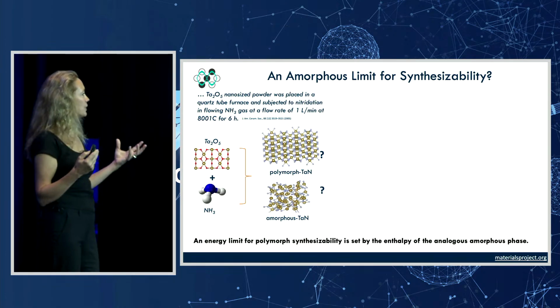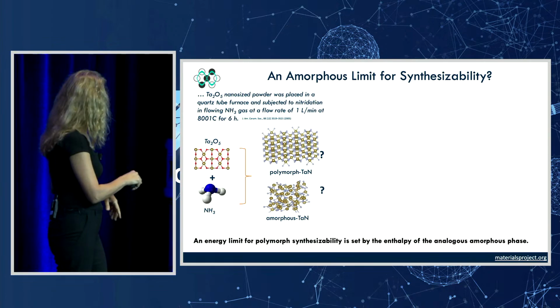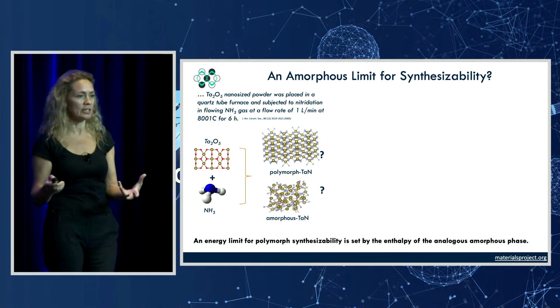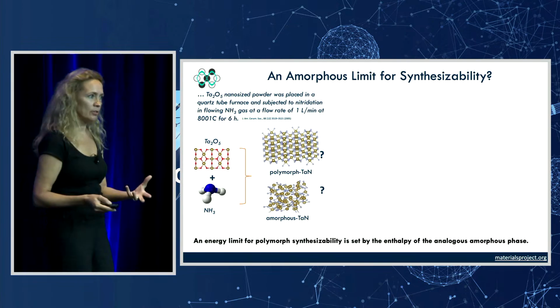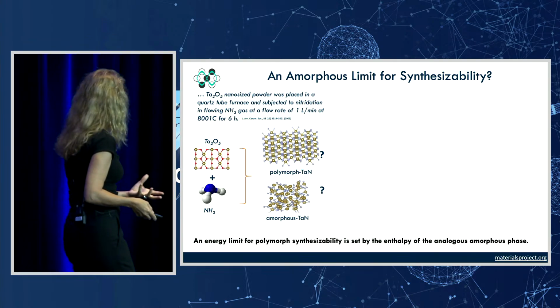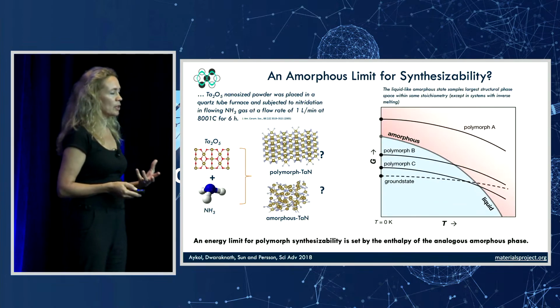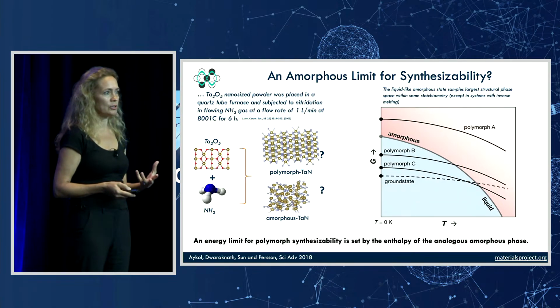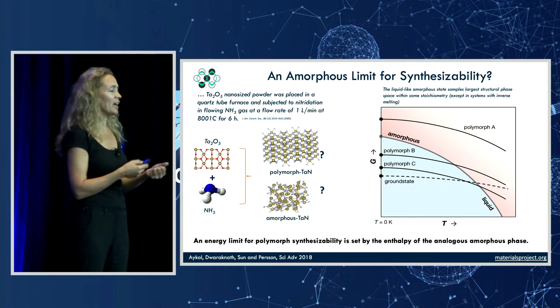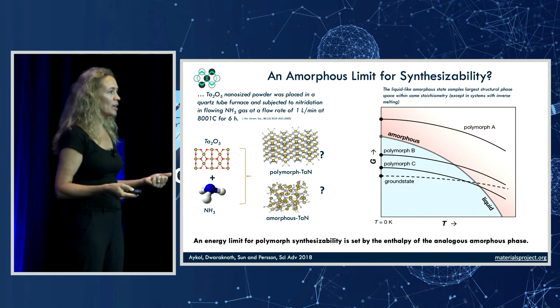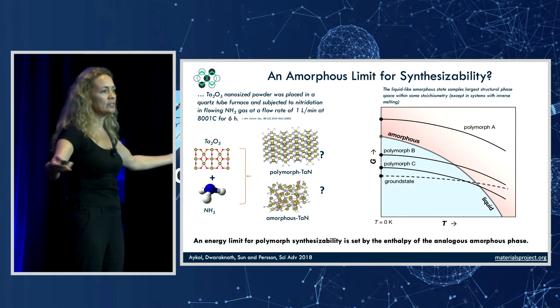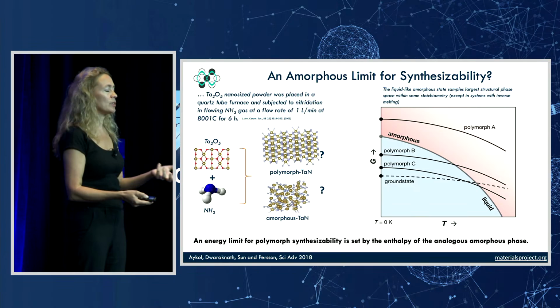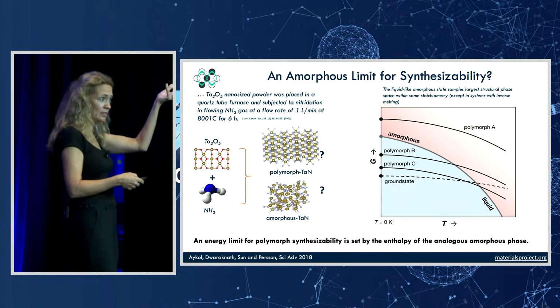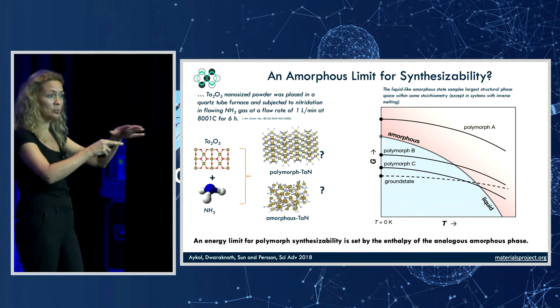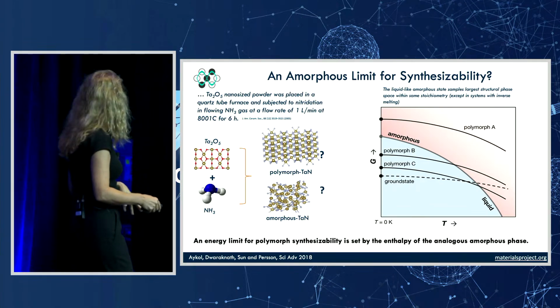So making something, kinetically, that could always be amorphous stuff, right? Kinetically, your amorphous state is always possible. But what about the thermodynamics of your amorphous state? So we can actually calculate a proxy for the amorphous state using computational workflows. It's not perfect, because we all know that amorphous materials depend on how you made it. There are many different versions of them. But we can take different kinds of snapshots and take an average and realize that, well, we're probably above the actual energy of the amorphous state, because nature is much better at exploring all those different variations than we are, but we can get an estimate.